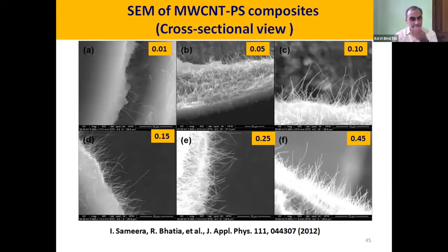So this was an interesting preparation of sample. We prepared samples of 1, 5, 10, 15, 25, and 45 weight %. We prepared these composite samples, and the thickness, as I told you, was about 60 micron. When a very sharp knife is used to cut this sample, on the cross section, if you can vertically align with the electric field, one can have better and desirable field emission properties from CNTs.